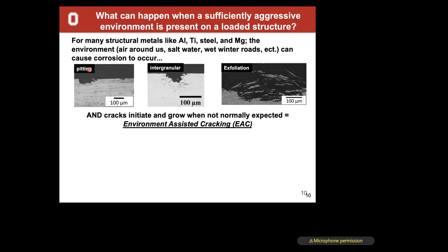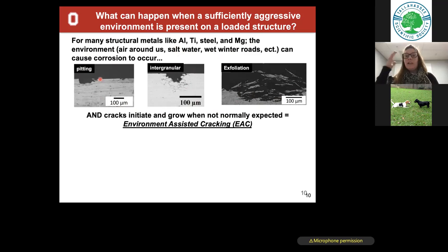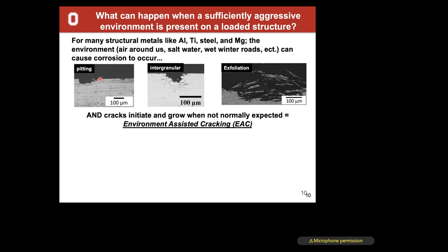That corrosion, just like you saw before, will look kind of like this. But what it also can do, particularly in these two situations, is cause cracks to initiate and grow when you don't normally expect them to. So when we make a thing like an airplane or a car, we bake into that, as engineers, assumptions on when that's going to fail. And there's certain tests that people do to know when it's going to fail and make sure you're operating safely. But as we know, and as I'll show you in a second here, there are accidents that happen. And those accidents happen because a lot of the time the environment causes those cracks to grow and initiate when you don't expect them to.